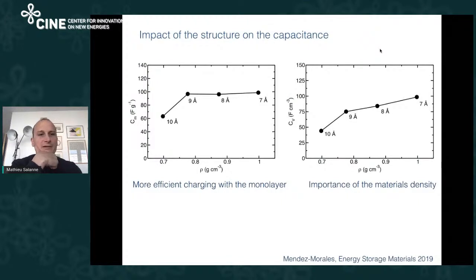In fact, when you have large pores, well, not so large, but 10 angstrom, you have 60 farads per gram, which is more or less the same as we had with graphite. And so we need to have smaller pores to increase the capacitance, and then we reach 100 farads per gram. If we look at the volumetric capacitance, there is an increase because the density is better. But the systems with small pores all behave more or less the same.